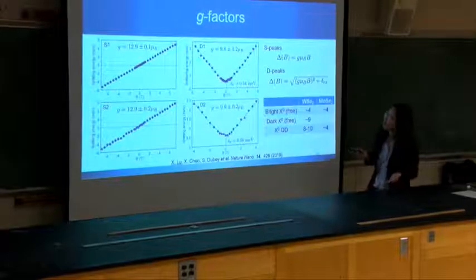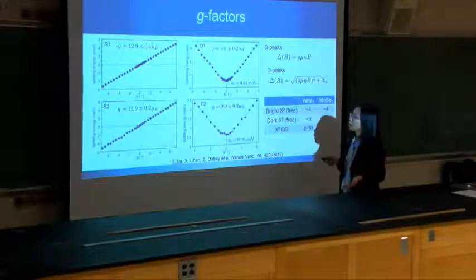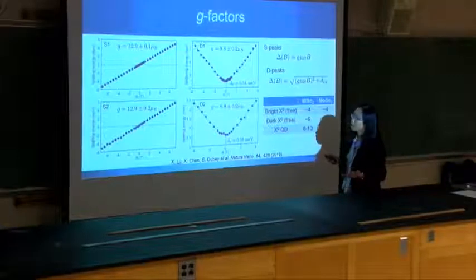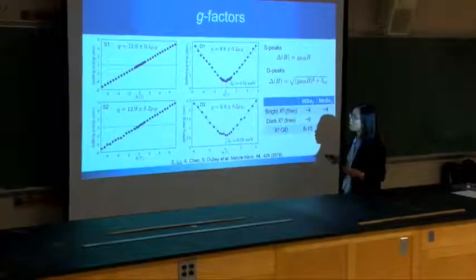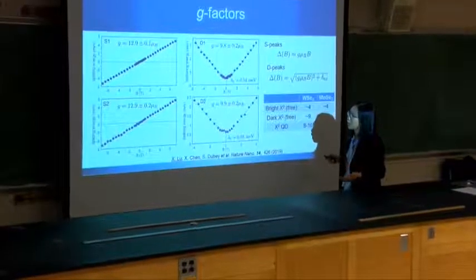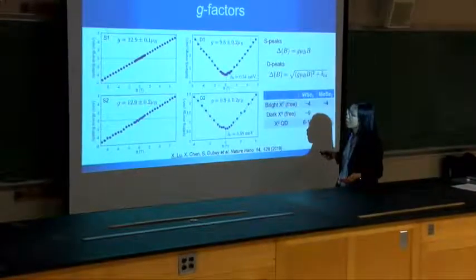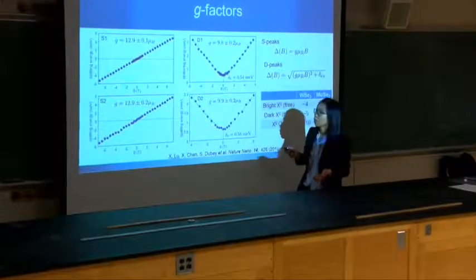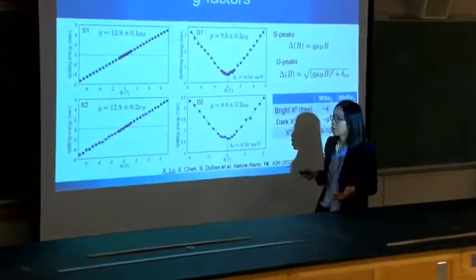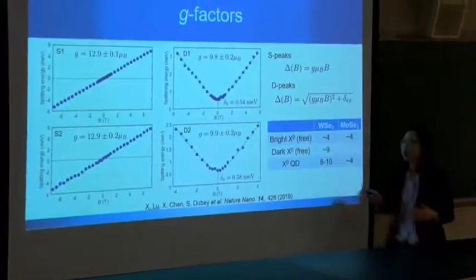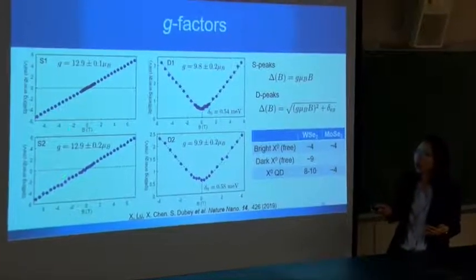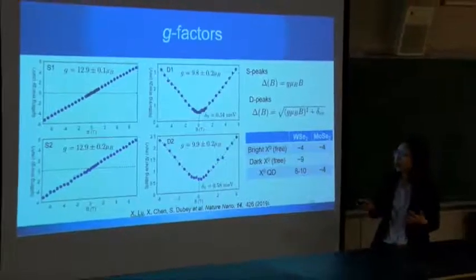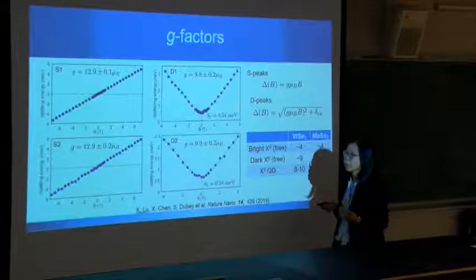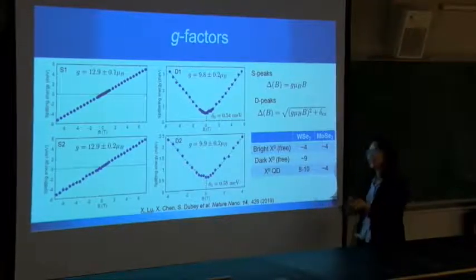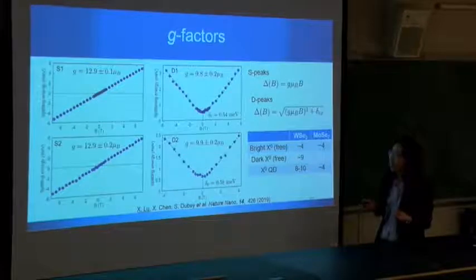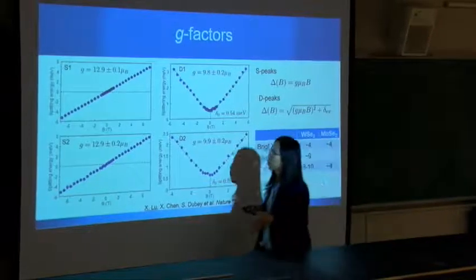And then in terms of the G factor, for the neutral dot, we have a G factor around 10. And this is actually consistent with the earlier measurement, suggesting that our assignment is correct. And for the charged quantum dot, we observe a larger G factor. At the time being, we don't have a clear explanation on why the G factor is larger. But a larger G factor, on the other hand, we're thinking that it could be a sensor, let's say, to sense a tiny magnetic field, although it needs to work at low temperature.